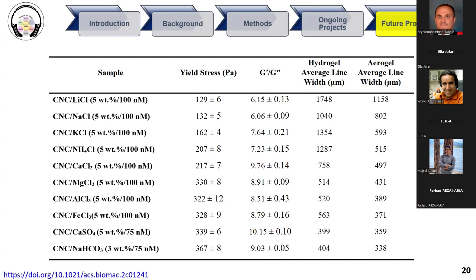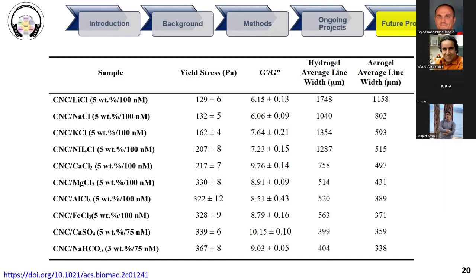As you can see in this table, by increasing the yield stress and G prime versus G double prime, we can have a better quality of printing. But the challenge here is that we cannot increase the yield stress as much as we want, because we need to apply a pressure on the system to overcome the yield stress, so the applied pressure should be higher than the yield stress. So we have a limitation here, but as much as we can, we need to increase the yield stress, while keeping it less than the applied pressure in the system.